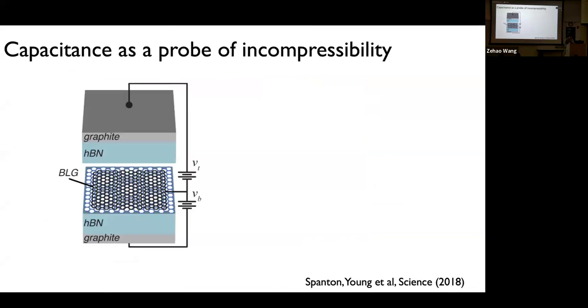And later, in 2017, 2018, there's a new experiment done at UCSB by Andrea Young's group, where they make two changes. The first change, which I won't go into detail about, is that they replace the gate material. Instead of using gold, which turns out to have many facets if you deposit it using an evaporator, they use graphite, which is much flatter and has much lower charge disorder, and it improves the device quality by many, many times. And the second advancement they made is that, instead of measuring resistance, they measure what's called a capacitance.